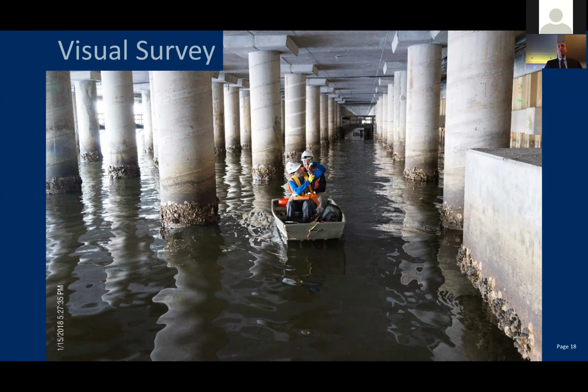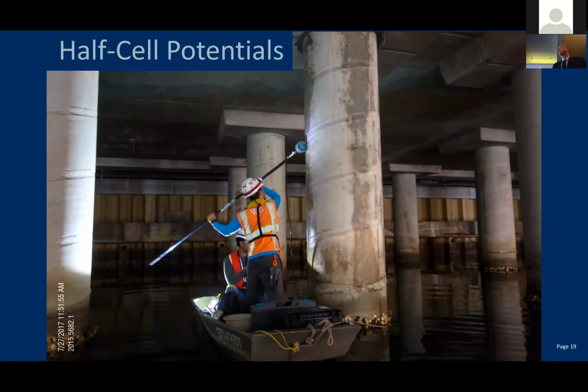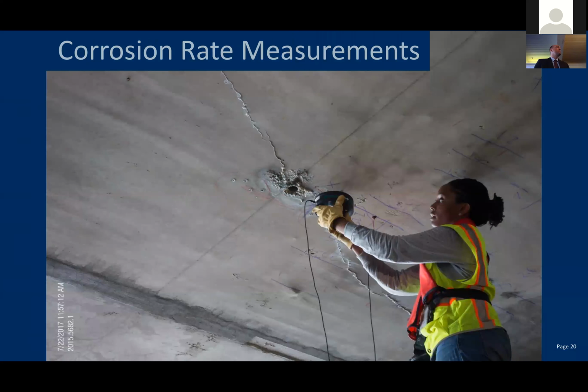In addition to the visual survey, we did half-cell potential, and this just gives you an indication of underlying corrosion that may be occurring. And so it can give you a characterization of low, medium, or high risk. And this is a non-destructive technique where there may not be indications of other distress. We also did some corrosion rate measurements, and the intent of these were just to understand how it correlated with our service life models. So we did this at various elements throughout the structure.